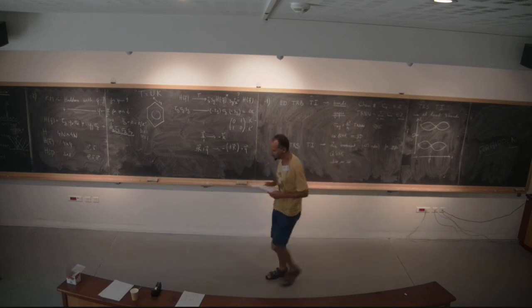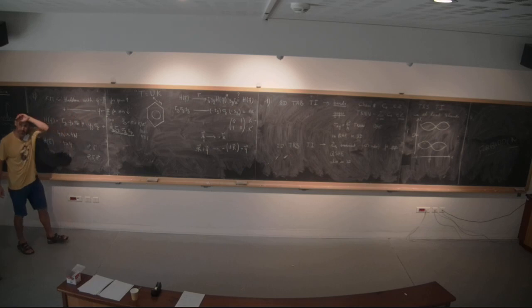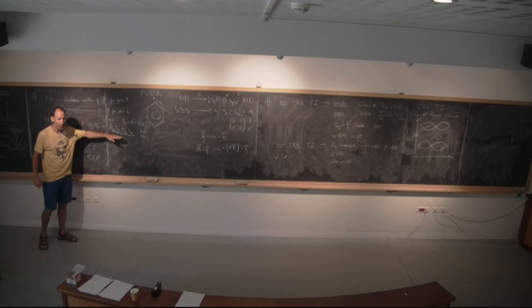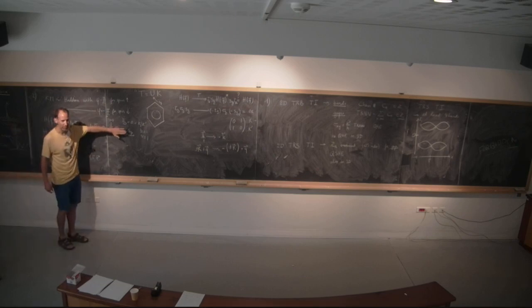So it turns out that in true graphene, such a term should be present in any description because it respects every symmetry of the graphene lattice. It has inversion symmetry, I didn't show it. Time reversal symmetry, also mirror symmetry with respect to the plane of graphene. So in principle, it should be there. In other words, the correct low energy theory of graphene should be something that has a gap. But it turns out that spin-orbit coupling is so weak in carbon, because it's a small Z atom, that this gap is not observed. It's too small. So the standard is to just take this number to 0.